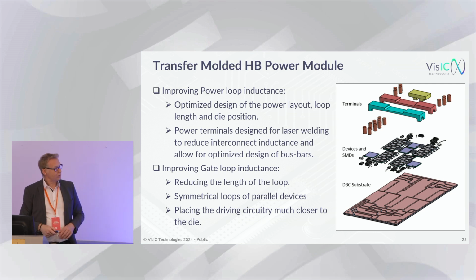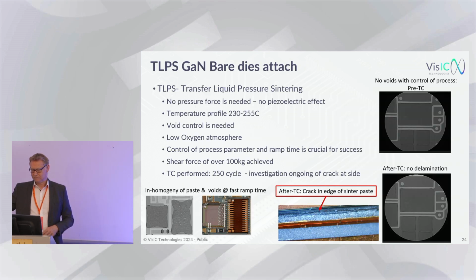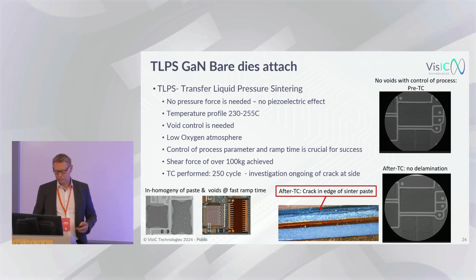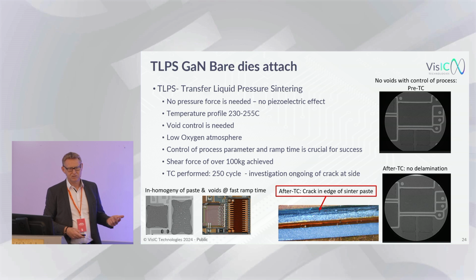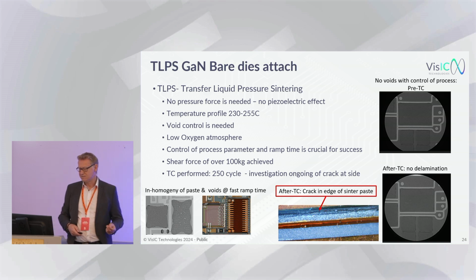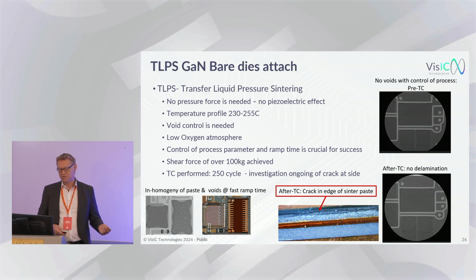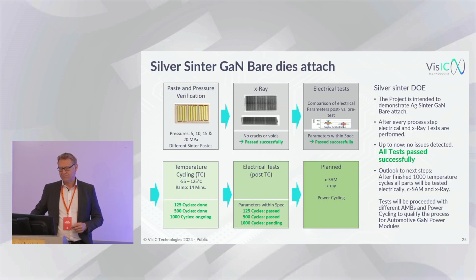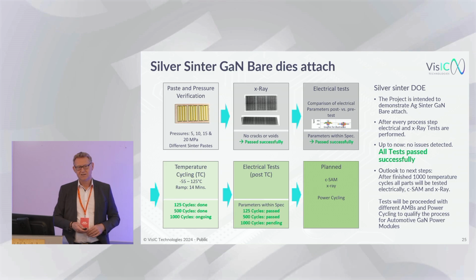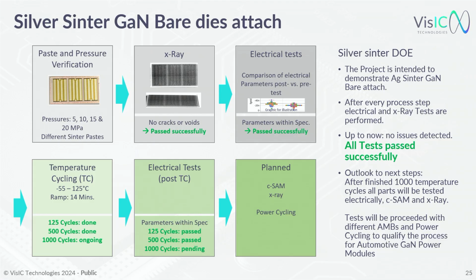From the interconnection, it looks very similar to whatever you do with standard products. You just do die attach, sintering, and then you connect the pins and terminals. Maybe two things about materials. We were also testing transient liquid phase sintering because we have a piezoelectric device, and from this point of view, we were trying to use a non-pressure material, which is TLPS. We saw some cracks, and we will still investigate this one. We were also doing silver sintering for this device, and even with 5, 10, 15, 20 megapascal, we have not seen any crack on the devices or change of parameter. And we even did power cycling measurement here.